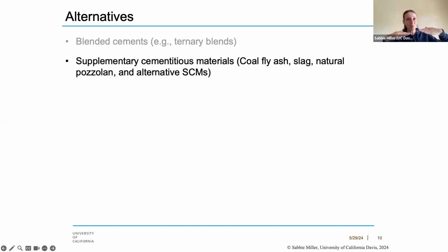Now, as we think about what we're adding to our blended cements, we also start to come across the discussion of supplementary cementitious materials. Now, by and large, in the US, we're adding our supplementary cementitious materials at the concrete batching phase, not at that blended cement phase where we're actually intergrinding with our cement product. But you can see these showing up in both locations. For the vast majority of our supplementary cementitious materials, you end up with relatively similar performance, whether you blend it in at the cement stage or blend it in at the concrete batching stage.